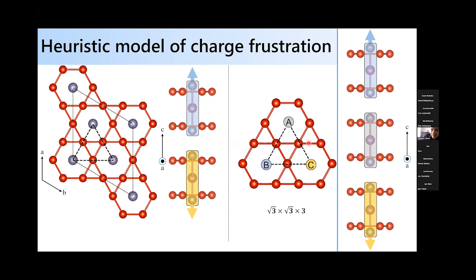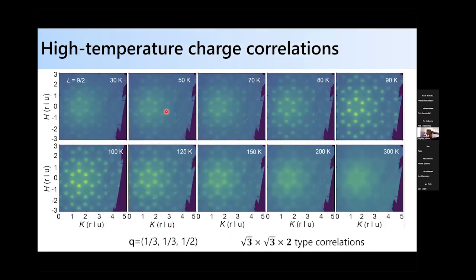Okay, so why is this significant? It implies that the structure that DFT predicts, this root 3 by root 3 by 2 structure, could potentially be somewhat frustrated in terms of forming long-range order, and that long-range order can't form until you realize this longer wavelength modulated structure, which is experimentally realized, which is this root 3 by root 3 by 3 structure. Experimentally, indeed, that's what I'm going to try and motivate is happening.